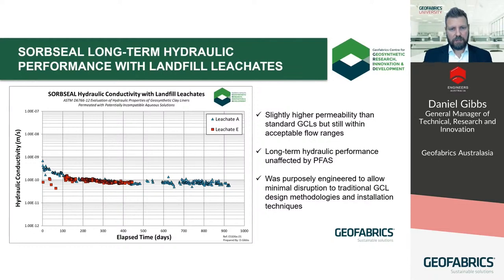So if we now look at the long-term hydraulic performance over a few years, we can see a slight increase in permeability overall, but still in the 10 to the negative 11s. These particular Sorbseal GCLs had a typical addition of around 1 kilo per square meter of activated carbon and between 4 to 4.5 kilos of dry bentonite.